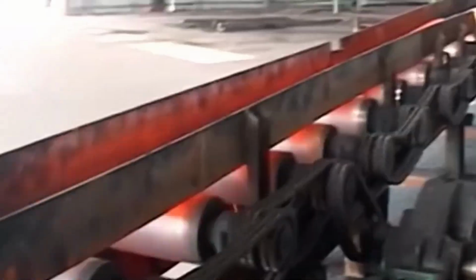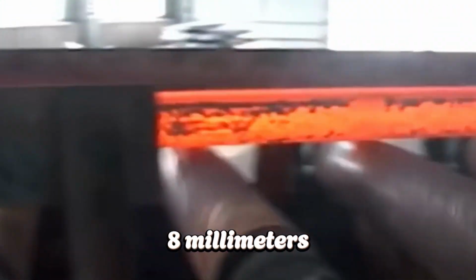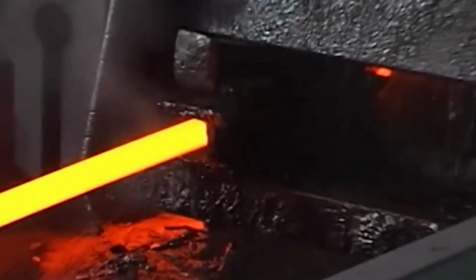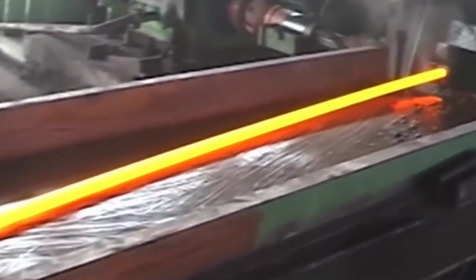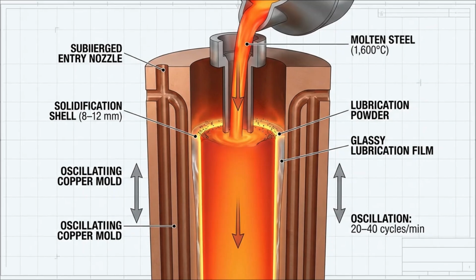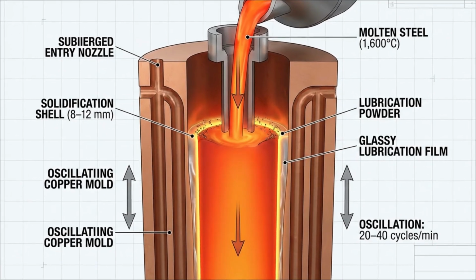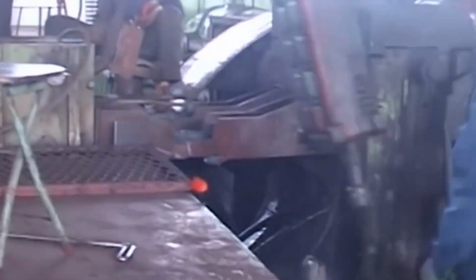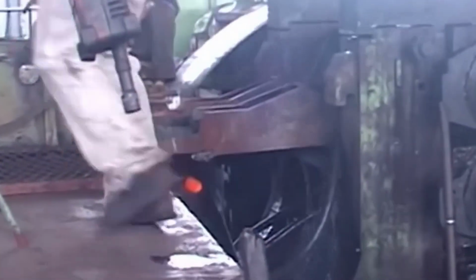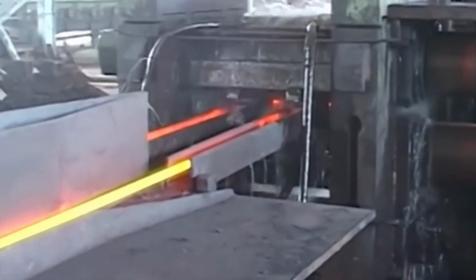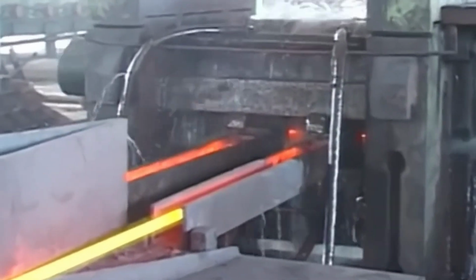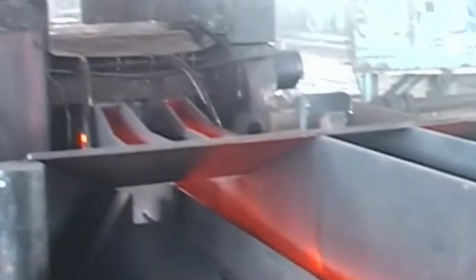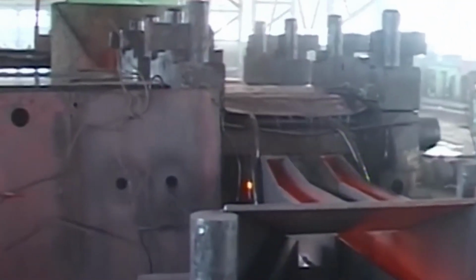If shell thickness drops below 8 millimeters, it tears. Above 12 millimeters, steel freezes to the mold. The strand leaves the mold while the core is still liquid. Rollers pull the billet downward as sprays cool the surface. Withdrawal speed sinks with solidification rate. If force rises even 5%, the shell tears.